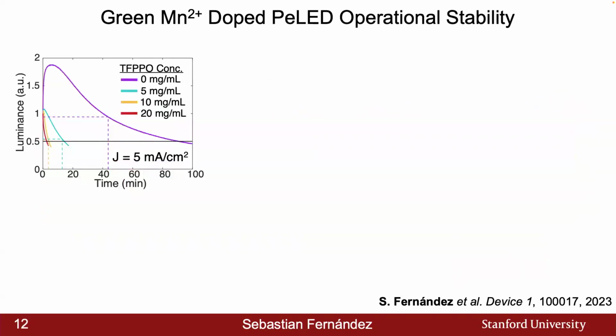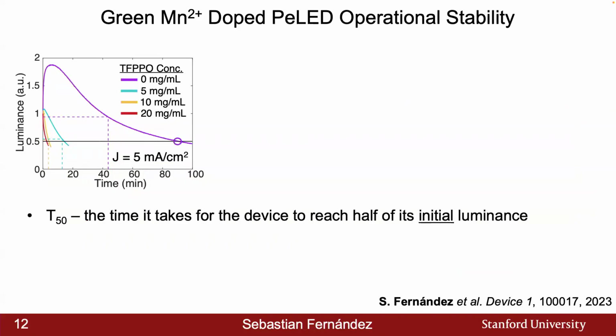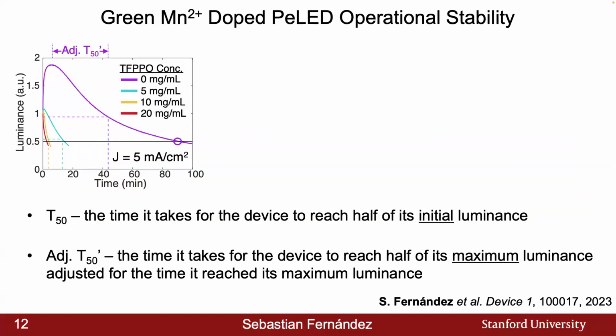So this is the luminance decay of the perovskite LEDs, so the figure of merit for the stability. And we can see that there are several half-lifetimes that we can extract, which I'll briefly define here. So the first one is the T50 time, which is just defined as the time that it takes for the device to reach half of its initial luminance, which for this violet curve is annotated with this violet circle. But you'll also notice from this violet curve that we actually achieve a luminance much higher than the one at t equals 0. And so in order to fairly compare, we also define an adjusted T50 prime time, which takes into account when we actually reach that maximum luminance, and then we look at half of that value to actually calculate the half-lifetime in that case.